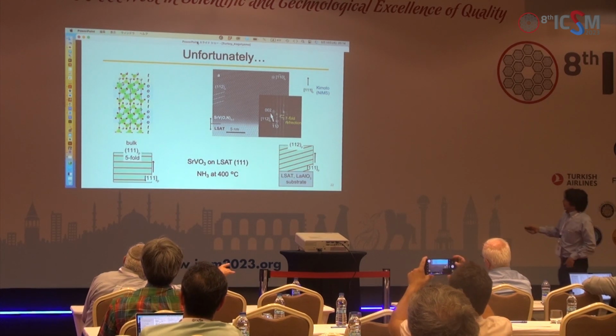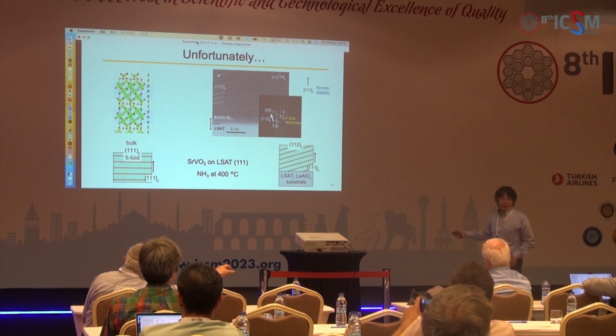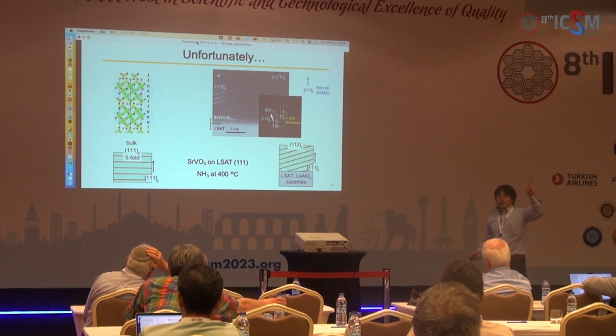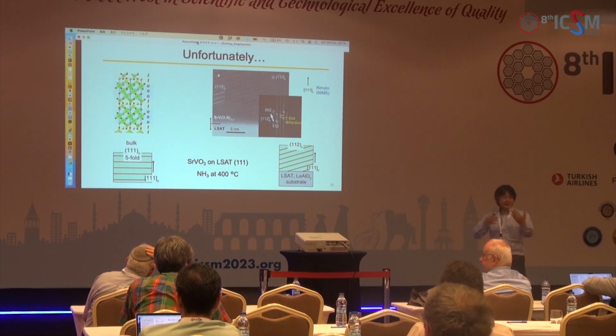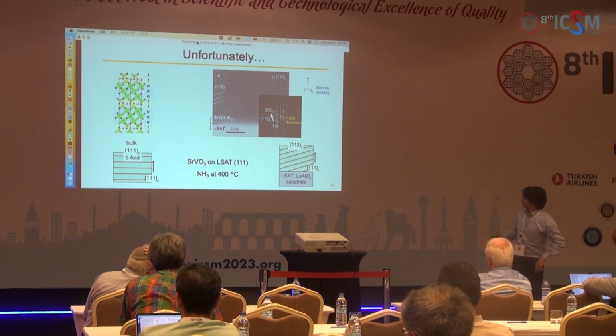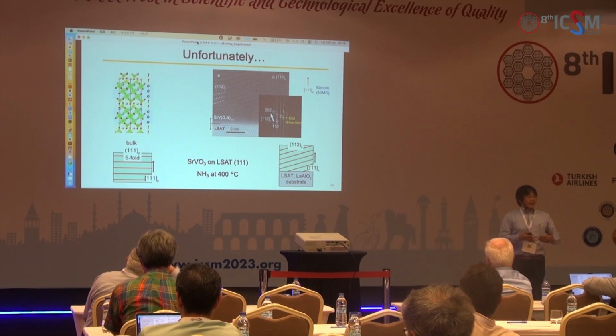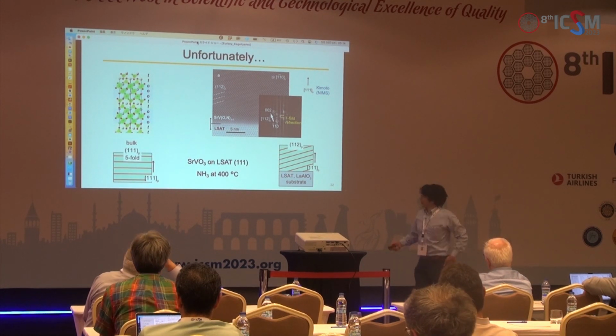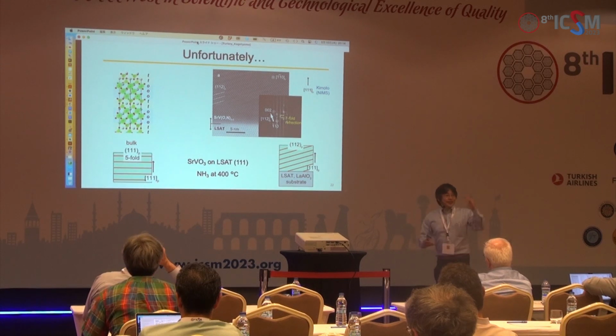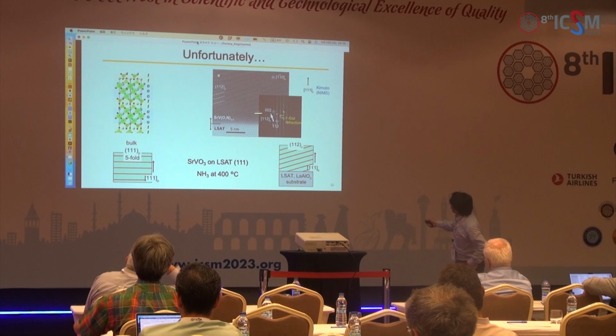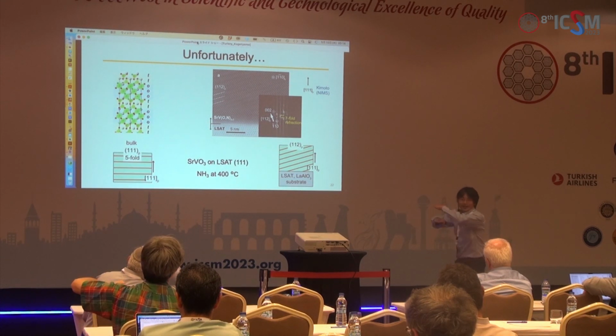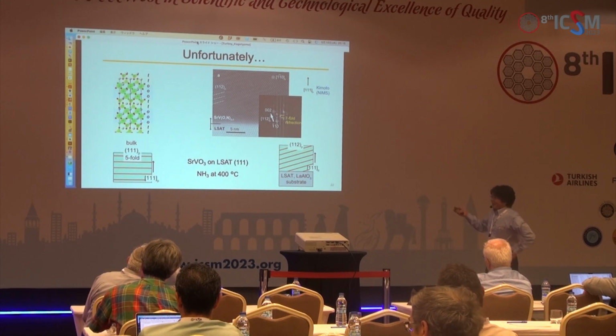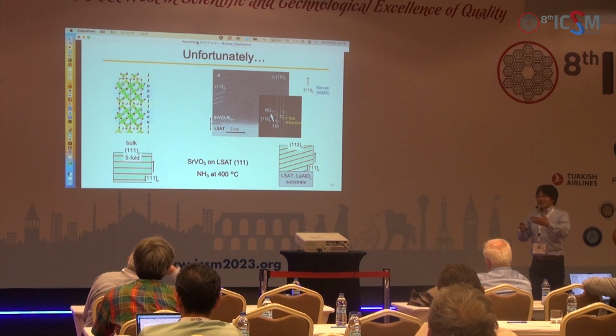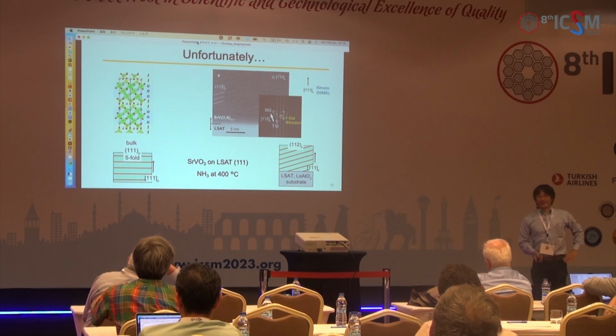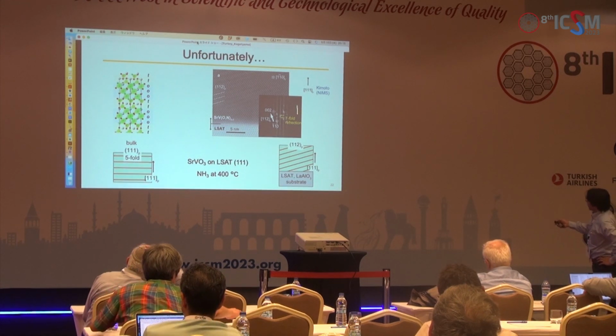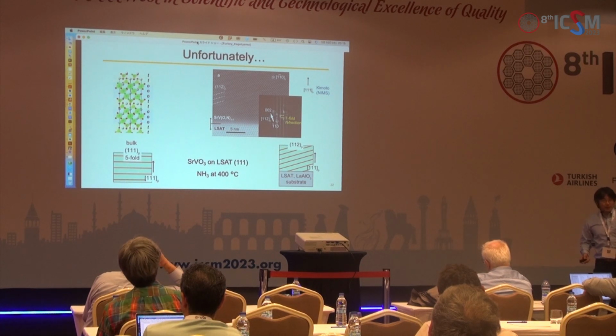What we expected was that we use this LSAT substrate and grow the strontium vanadium oxide parent material. Then we did similar reactions using flowing ammonia gas. But my colleague came to me and said, unfortunately, he failed to obtain a single crystal. If this is the 111 direction, and we obtain the expected single crystal, we should have some kind of stripe like this. But this is not parallel, it's tilted. But actually, I was so happy to see this because this is kind of changing the oxygen vacancy areas. From some analysis, we found that this is the 112 direction, not 111.